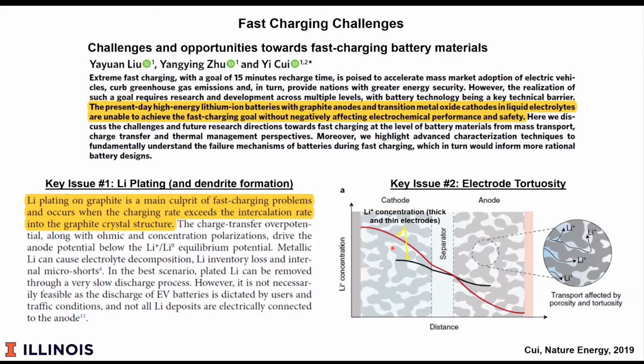And so ideally, the cathode would have a tortuosity of 1, meaning that the ions could enter the electrode, and if there are channels, the channels would be perfectly straight. But that's, of course, difficult to engineer in practice. And this applies both on the cathode and the anode. It's a particularly significant problem on the anode because the anode is made of carbon flakes, and the flakes tend to lie flat. And so if you have a flake-like morphology, the tortuosity only becomes worse, which then feeds back into the lithium plating issue.